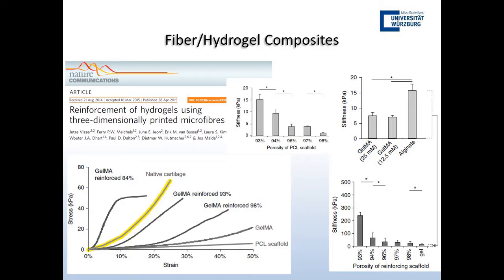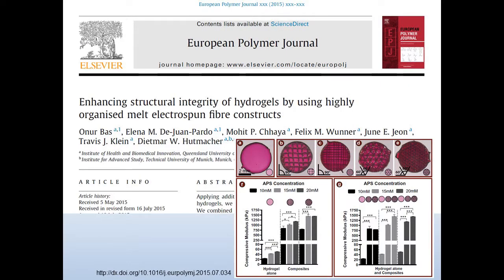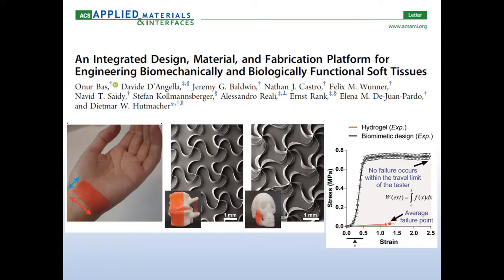For melt electrospinning, a lot of fantastic papers are coming out from this. And this was really, I think, the time people realized that there's something in here. You've got your hydrogel alone, and then you have your composites, and there's always this bar between them, showing that there's this massive strengthening effect by having melt electrospinning fibers. These are in straight lines, but also a great example here of printing in sinusoidal structures, where you can create this the hydrogel alone.